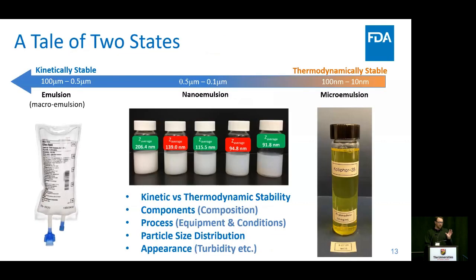And so if we look at what the difference is between, say, a macro emulsion, a nano emulsion, and a micro emulsion, really the distinction here is that we have a thermodynamically stable system and a kinetically stable system. And so as we'll go into here in a second, you can basically formulate these at the exact same composition, but then by using different processing conditions or processing equipment, you can influence the particle size distribution, and that particle size distribution is what is giving you your physicochemical properties.